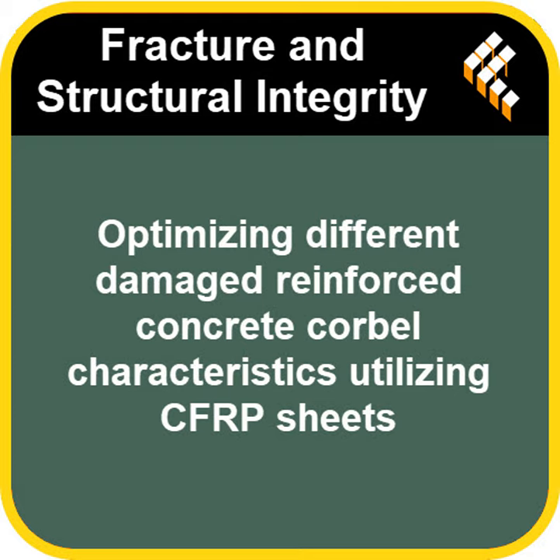Right, less deflection under the same load if it's stiffer. Precisely. The side-wrapped, undamaged specimen, SCS-01, showed a massive 52.15% increase in stiffness compared to the control. Over 50% stiffer. Wow. And consequently, its displacement, its deflection at peak load, was 21.3% lower than the control. That's a big difference in how much it would sag. Definitely. Even the strip-wrapped undamaged one did well, 47.4% stiffer and about 18.7% less displacement. So both methods significantly stiffened the undamaged corbel.